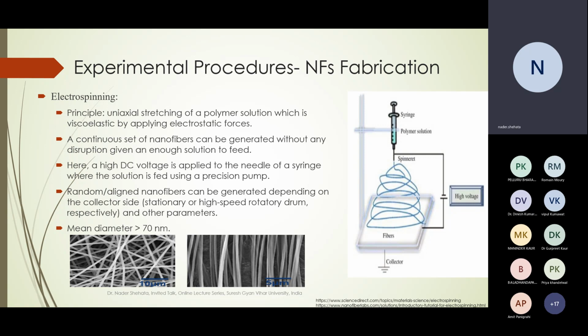Then the DC high voltage could help to withdraw the jet of the nanofiber coming from a precision pump, and then the formed nanofibers could be received on a metallic collector as shown here, or this metallic collector in some applications could be replaced by a high-speed rotatory drum. The difference between both, as shown here with the simple SEM images as examples, is that whenever you are generating the nanofibers